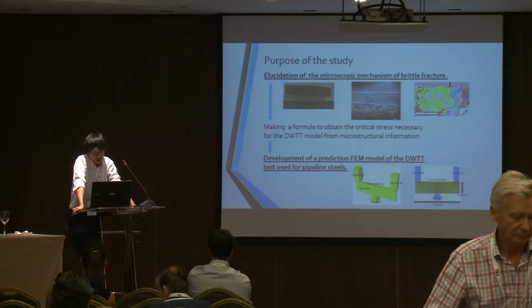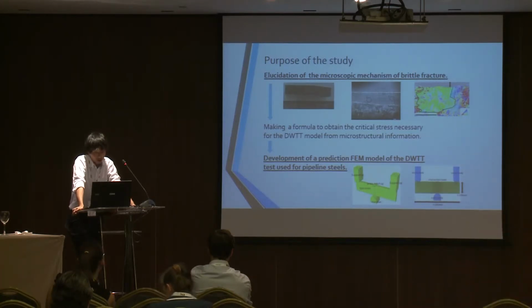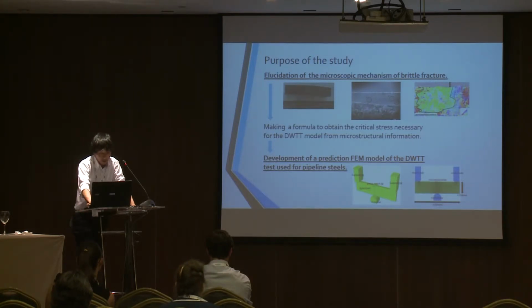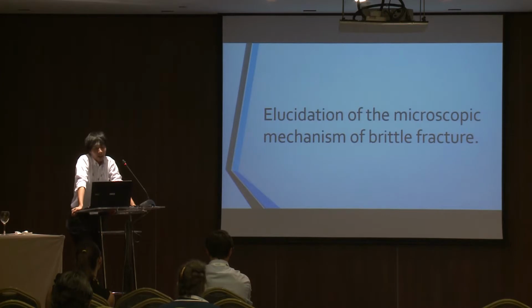In this presentation, the formulation in the second purpose is not presented because we didn't get enough results. Therefore, in the third purpose, analysis was performed using the critical stress derived from the double notch test, and the validity of the analysis was verified. First, I'll talk about elucidating the microscopic mechanism of brittle fracture.